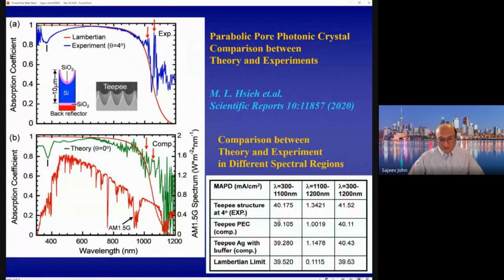The theoretical estimates shown in the first two columns are slightly below that. That's probably because we didn't have an exact rendition of what the actual structure is, and we were dealing at a slightly different angle of incidence than the experimental structures. But this does show very clear evidence that one can exceed the so-called long-standing Lambertian limit.